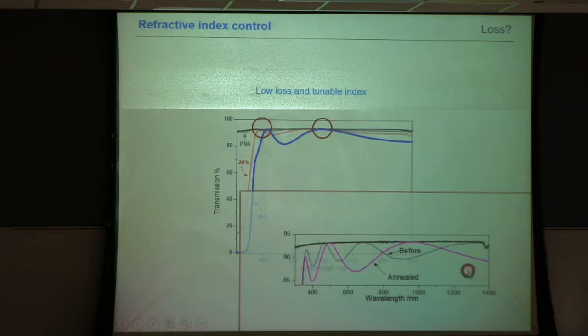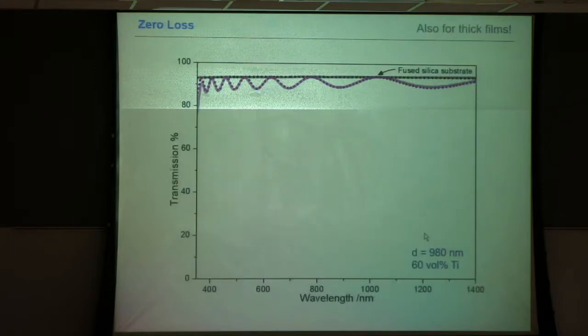As I mentioned, when we anneal, we increase the refractive index, oscillations get deeper, but we still have the same intensity maxima. And that's actually a bit surprising because people always worried, well, you use polyvinyl alcohol. Everybody knows when you heat plastics, they're not really the most temperature stable materials around. However, because we actually consume the alcohols with the reaction to titania, one of the most prominent degradation mechanisms for PVA is hindered. And we can do that for thick films. Clearly, you can argue what is thick. In our field, 1 micron is actually pretty thick. And then you see beautiful oscillations, and we hit the transmission maxima.